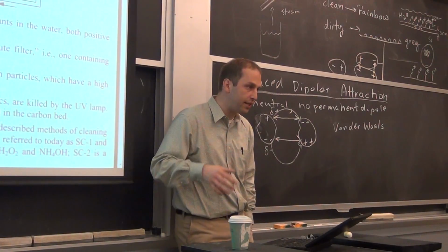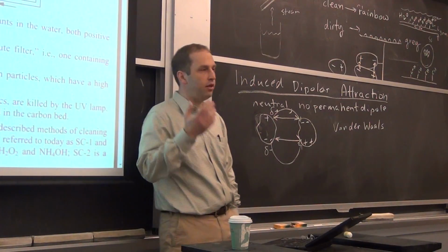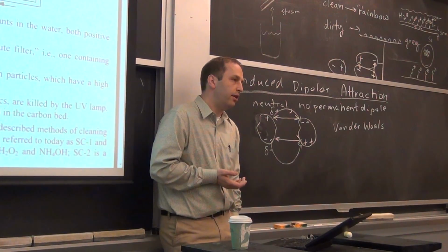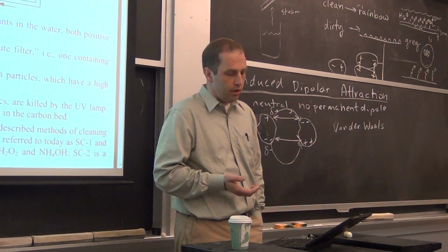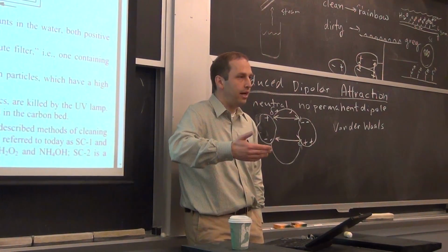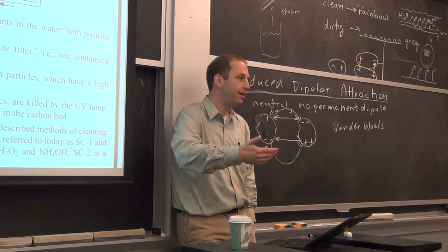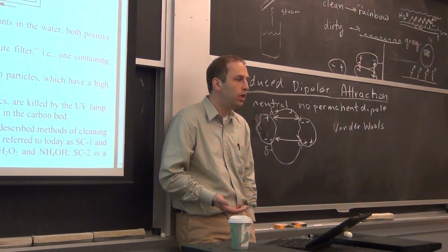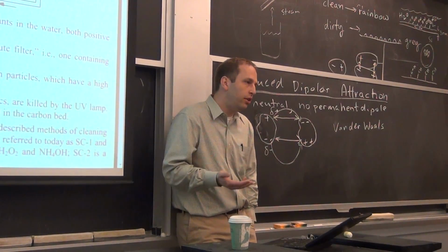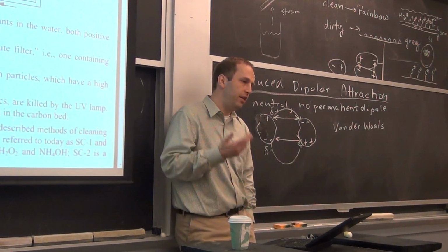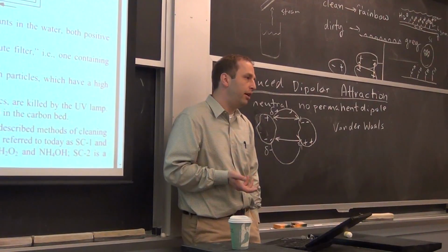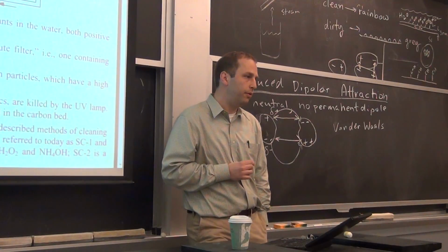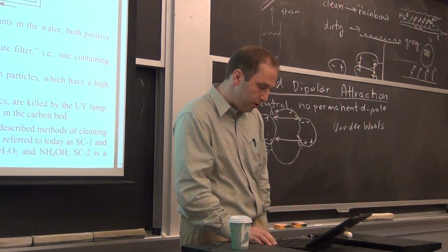So there's a number of materials. This can happen to your substrate too. We just recently learned that magnesium oxide, which we've been working with for a long time, is etched by deionized water. Luckily it hadn't been affecting the process, but we're considering adding a deionized cleaning step to the process, and it was recommended by the supplier of the material, and it seemed like a very innocuous thing to do. But before we did it, we first did a literature search and then checked ourselves and discovered indeed that magnesium oxide is etched by deionized water. Very low rate, but enough so in our case it would certainly have killed our devices had we undertaken that. So be careful when you're using deionized water.